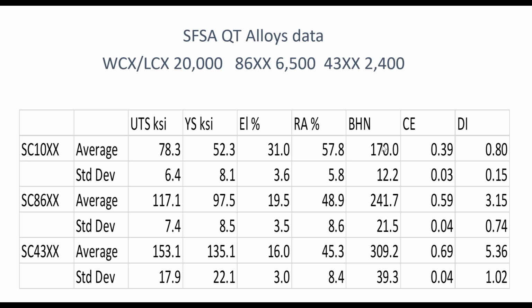This is the average properties we have for the quenched and tempered materials. And then I can calculate the carbon equivalent and DI. And so if I want, from that scrap pile, to make something that's carbon steel, I'm going to shoot for a carbon equivalent and DI so that I can get the properties that I want.